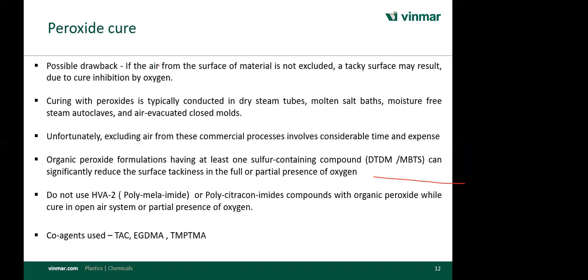In most of the industry, when they first try the peroxide cure, they find that the cure is not proper, but actually curing took place. The culprit for the peroxide is the oxygen. So we have to eliminate the aerial oxygen or the oxygen present in the moisture. Practically 100% exclusion of oxygen from air or moisture from the system is not possible, except if you cure in the salt bath method. So we recommend with peroxide, please use some sulfur donor like DTDM or MBTS, some 1 to 2 PHR. It will give you a lot of liberty to process your compound with peroxide cure in your system.